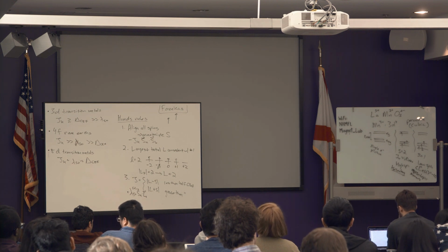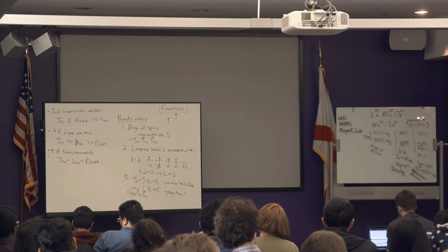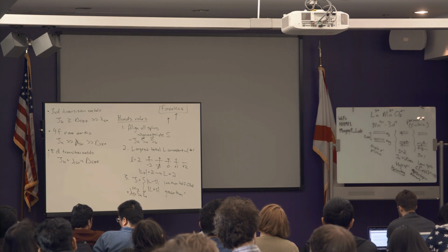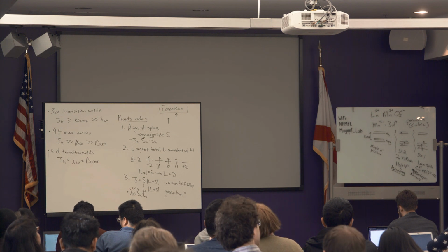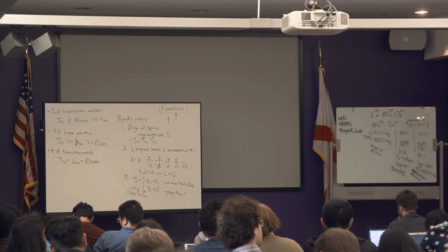So nothing is connected here, so it's definitely only going to have expectation of Jz. So this is one of the ways that you can get away from these Heisenberg moments, and you really have pure Ising moments when you have this doublet here.